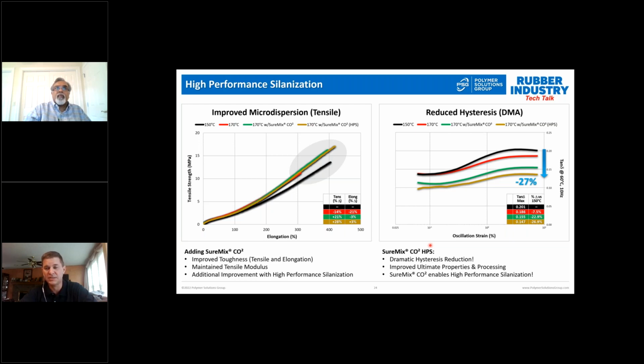As much as 27% reduction, and you'll notice that even with the reduction in the silane, we get a dramatic reduction in the hysteresis. In fact, it's a little bit lower than the compound without the reduction in the silane. So this dramatic reduction in the hysteresis shows you how powerful SureMix is for hydrophobating the silica and achieving the silica dispersion to get that low hysteresis result.